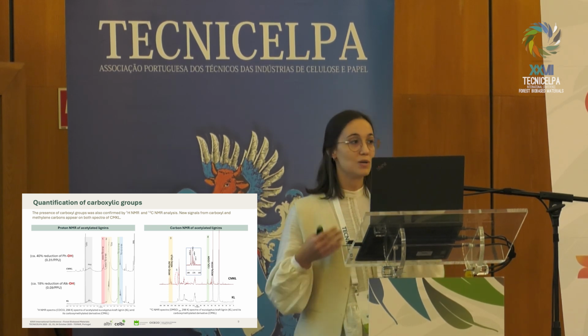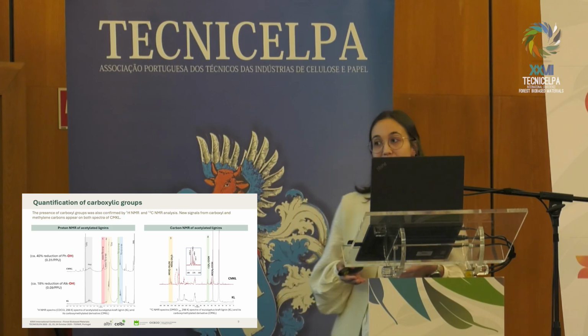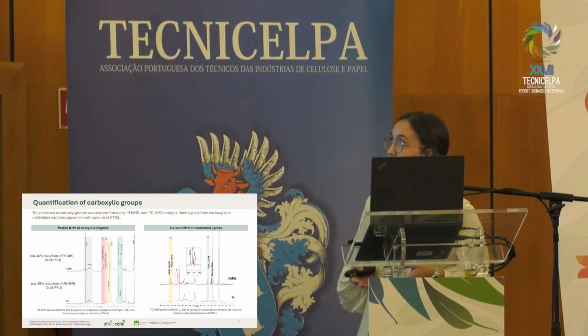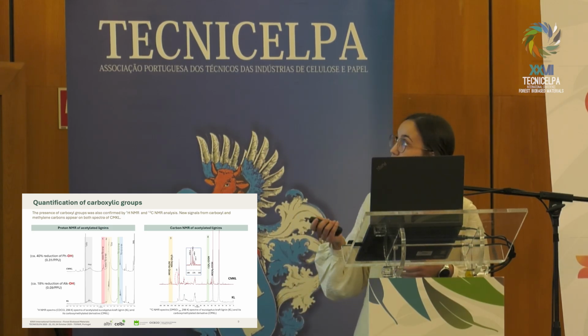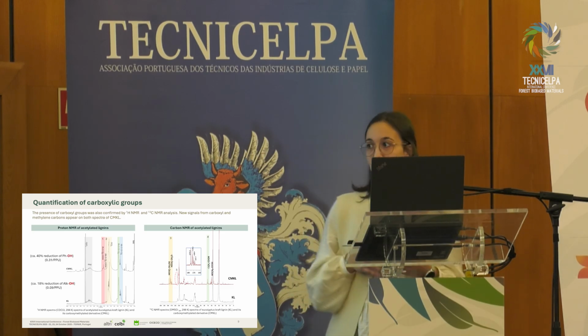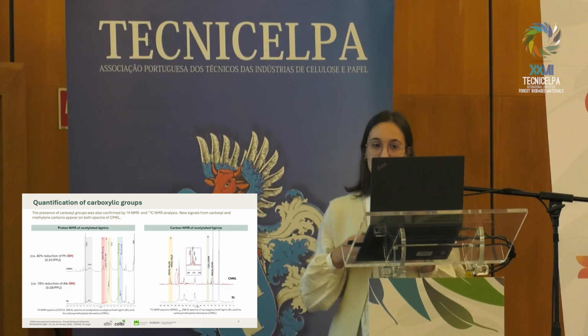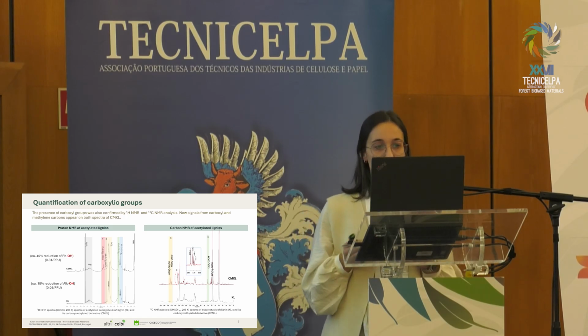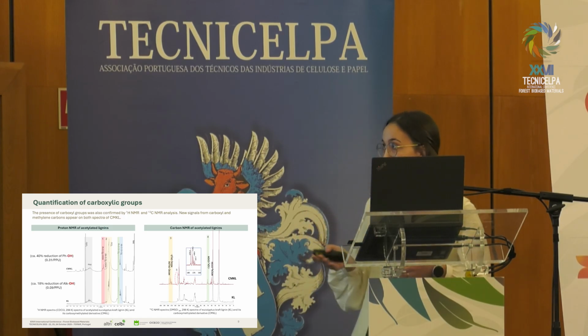Those conditions were applied at the pilot scale, and the obtained modified KRAFT lignin showed a degree of substitution of 0.41, which was slightly lower than the one obtained at the lab scale, which was about 0.45, but within the reported range of values.